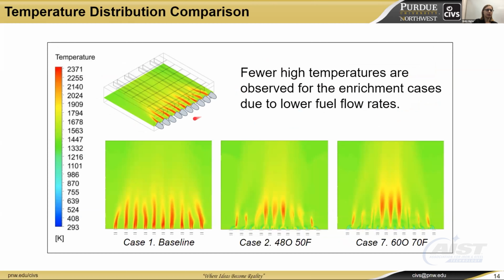This slide shows a comparison between a horizontal burner and port midplane within the fluid region, and we can see the baseline temperature. We have higher temperatures occurring near the burners, whereas for the enriched cases, we do not have as many high temperature regions occurring. Those that do occur start further into the furnace and are in line with the ports. However, the moderate temperature area, and it may be a bit difficult to see, appears in yellow here, and we can see for both of these cases it actually extends all along the middle of the fluid region, all the way through the furnace, whereas for the baseline case, moderate temperatures tend to occur closer to the burners.